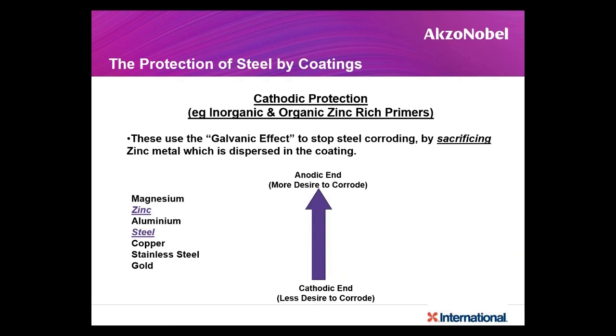And this method of applying zinc, or a more reactive material, on top of a less reactive material to protect it is called cathodic protection. Here zinc is a sacrificial anode pigment. Normally, where do you find zinc usage? You can find zinc in hot dip galvanizing, where you pass the steel through molten zinc and galvanizing happens on the surface, where the layer of zinc on top reacts with the environment and protects steel. Similarly, you can add zinc in paint, and zinc rich coatings are applied.